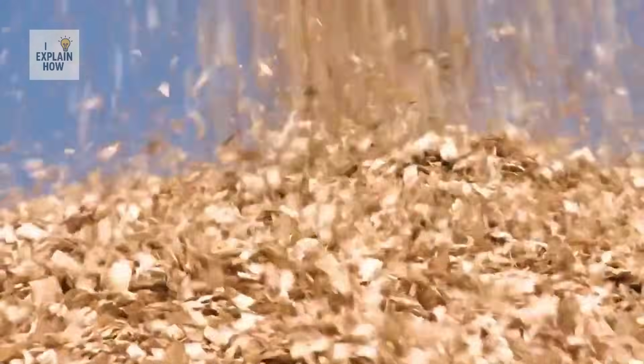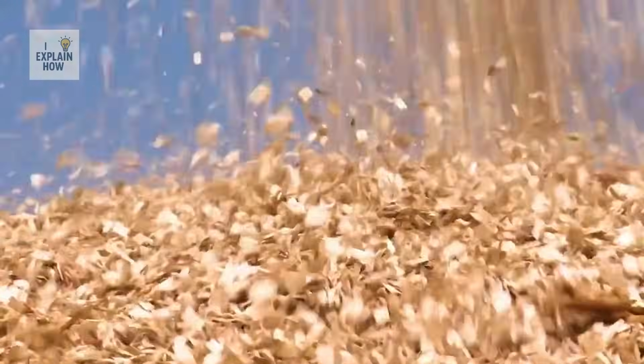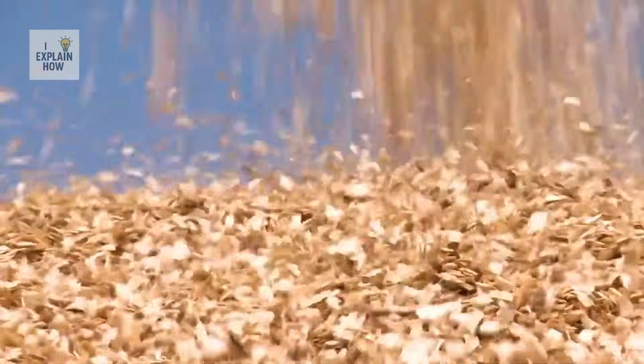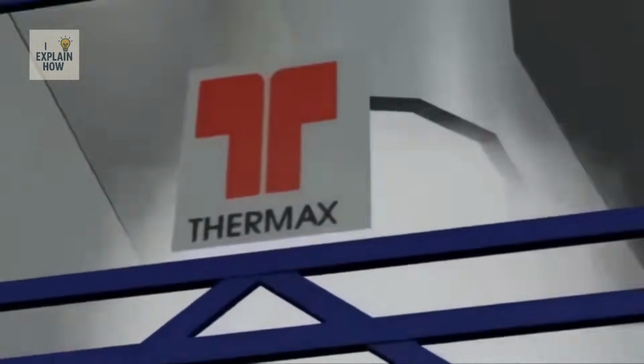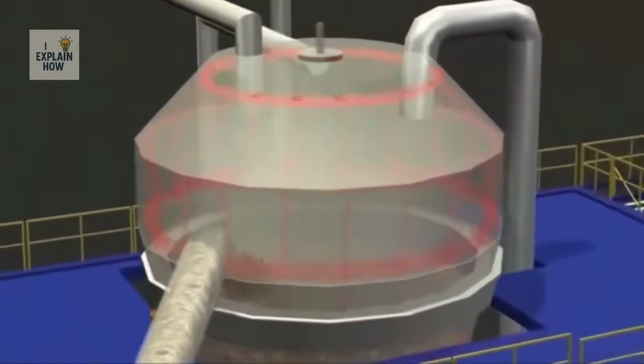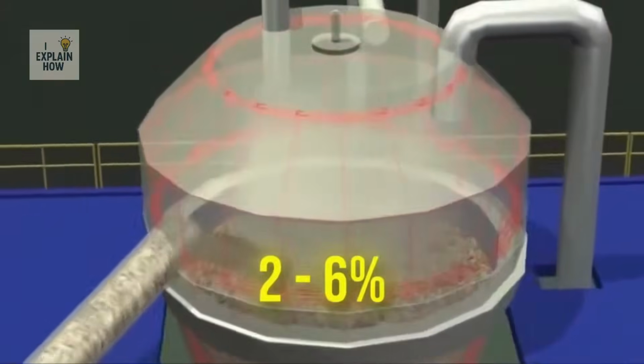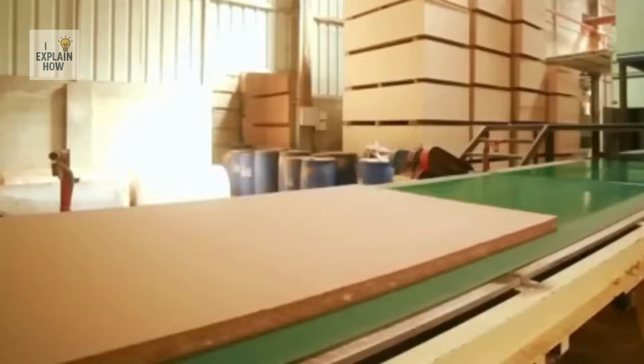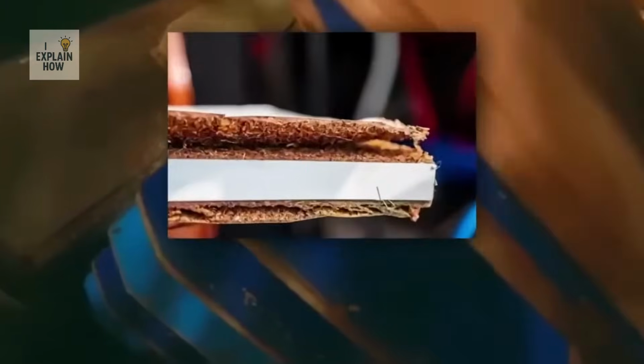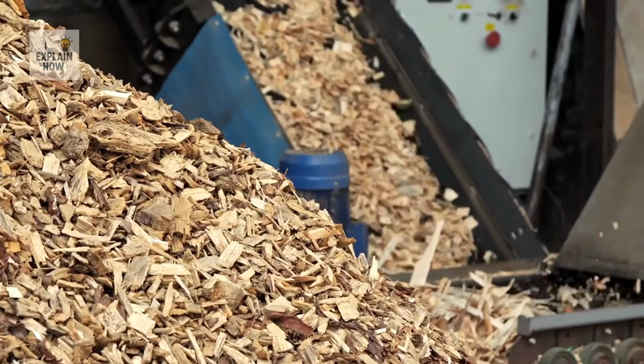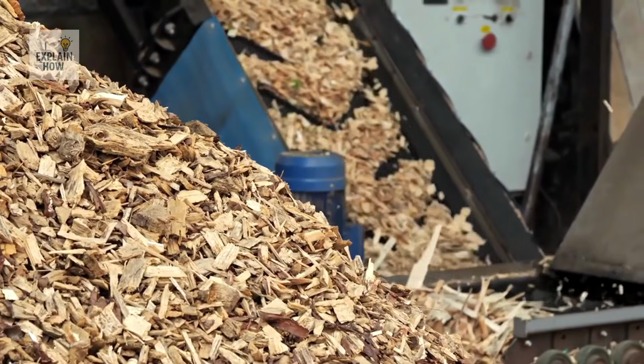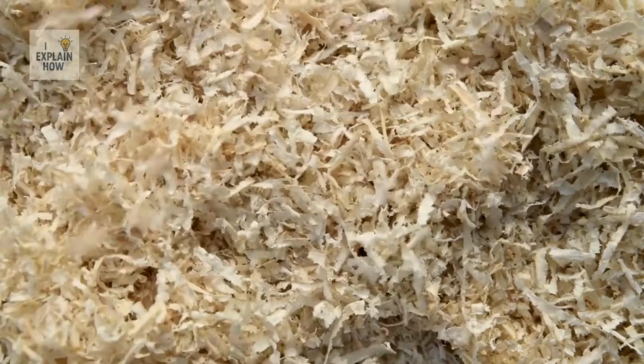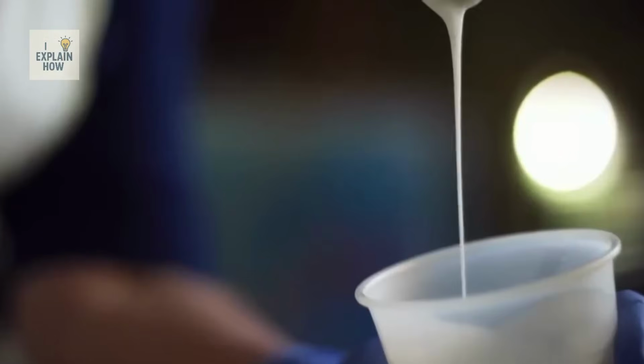But before assembly, the chips have variable moisture content, unacceptable for quality bonding. They therefore pass through enormous rotary dryers filled with hot air. Automated control ensures a strict moisture level, between 2 and 6%. Excessive drying prevents proper glue absorption. Too much moisture would cause internal cracks during pressing. After drying, the chips are sorted by size and weight. The large ones fit the inner layer, the fine ones form the outer layer.